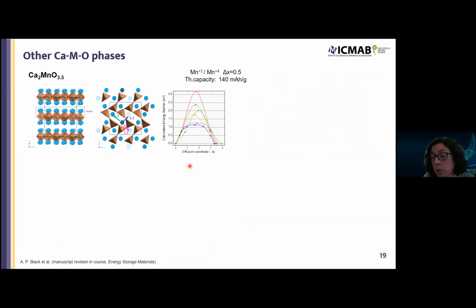And finally, I would like to mention other two cases which we investigated, again in collaboration with Elena Arroyo in Madrid, who did some screening of different calcium transition metal oxides to look at possible migration paths for calcium in the crystal structure. And when she found low energy barriers, she came to us to pursue the experimental study. So the first interesting compound is calcium-2 MnO3.5. This is a derivative of the Ruddlesden-Popper phase calcium-2 MnO4, which has some oxygen vacancies, which one can see very clearly on the AB plane.